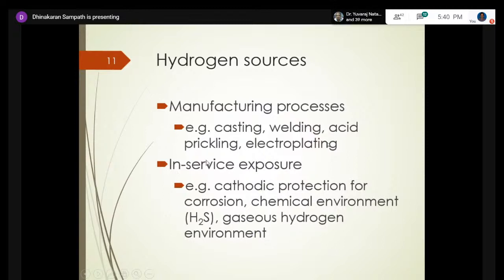And in-service exposure is very complicated, because hydrogen is there throughout the life of the material in service. A few examples are cathodic protection or corrosion of the material. Sometimes it will hit an overpotential, which leads to excess hydrogen generation. And some people say that in air, due to moisture, we'll have hydrogen entering the material. But it depends, once it reaches some critical concentration, it'll also be detrimental. And as I said, there is the gaseous hydrogen environment.